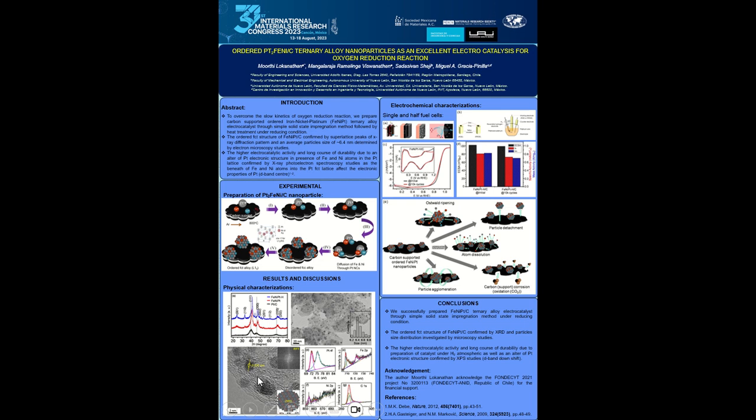Further, high resolution TEM microscopic images confirm the presence of a d-spacing with a value of 0.23 nanometer. This corresponds to (111) facets. So the nanoparticles have (111) facet surfaces on their outer layer.